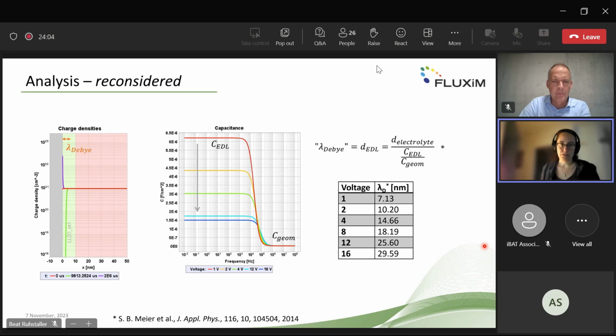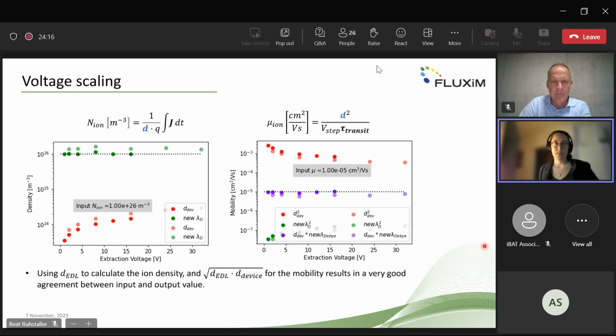So this was just another simulation where we looked at how the capacitance scales at different offset voltages. And if we now use this thickness in the analysis, instead of the device thickness, we can actually get a very good agreement with the input value. So here in green, you see the new thickness that we used. And also if we now slightly modify the analytical formula for the mobility, we can see that if we use the square root of this electric double layer times the device thickness, we get a very good agreement with the input value. So that was very promising.